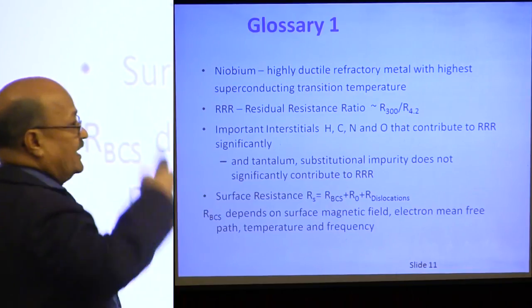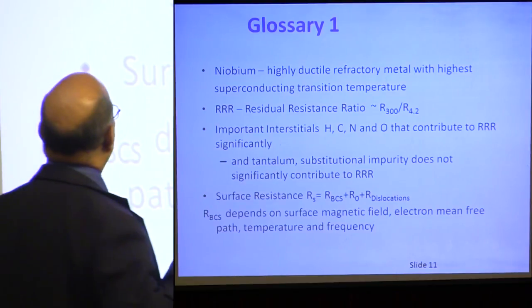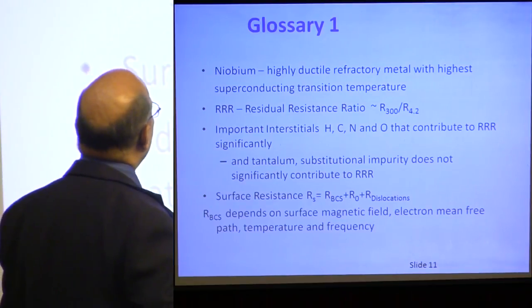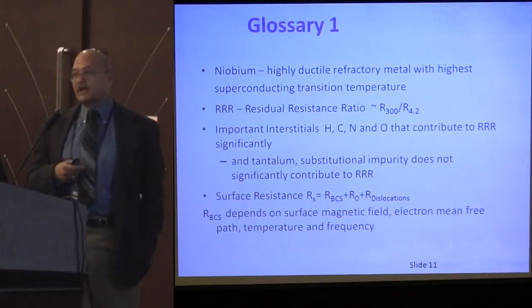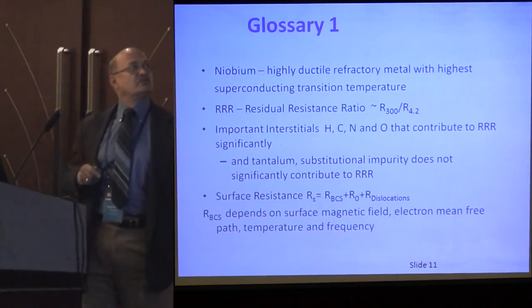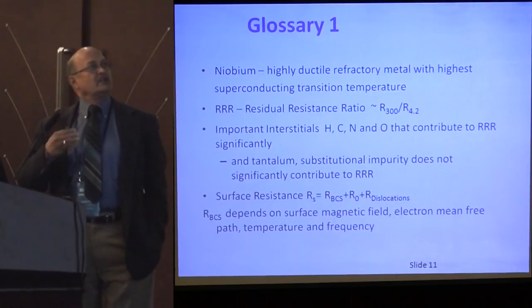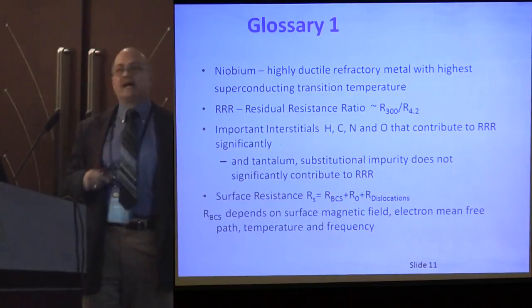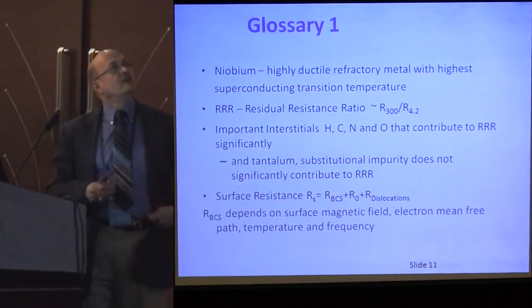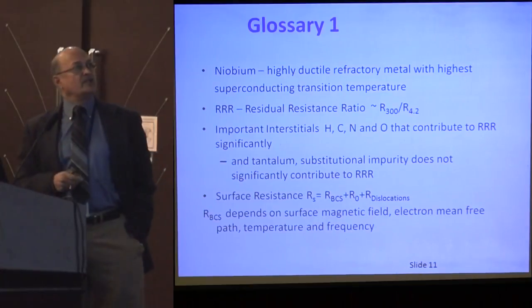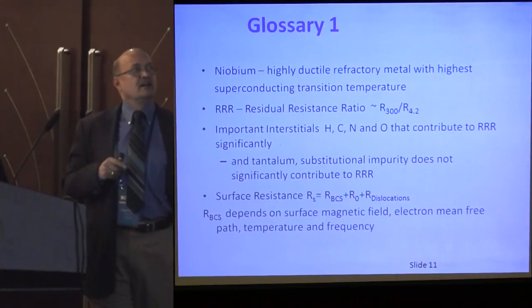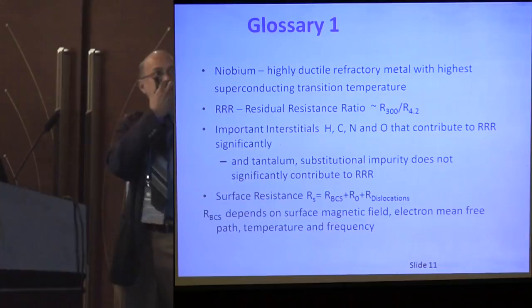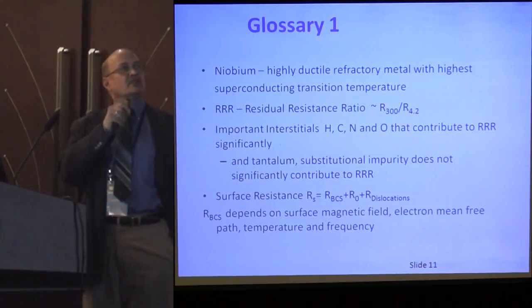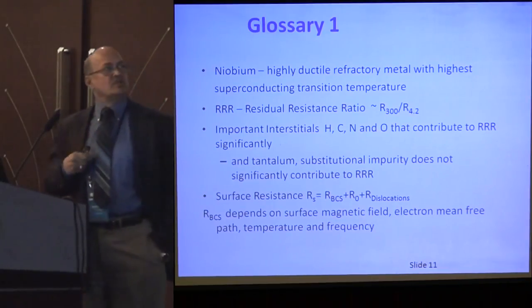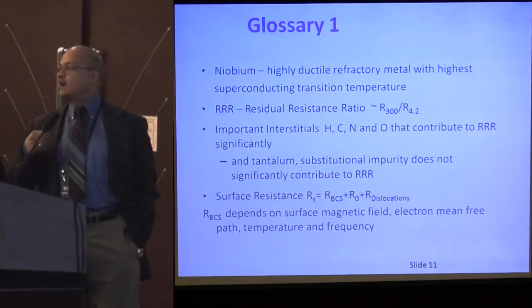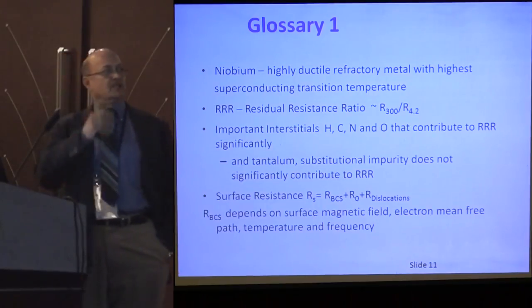The material used for this accelerator structure is niobium, which is a highly ductile refractory metal with the highest superconducting transition temperature of 9.25 K. The purity of the material is defined by the residual resistance ratio, RRR, R300 by R4.2. The important interstitials, hydrogen, carbon, nitrogen, and oxygen, contribute mostly to the RRR, and there is a substitutional impurity, tantalum, which does not really affect RRR. So I want you to keep that in mind.